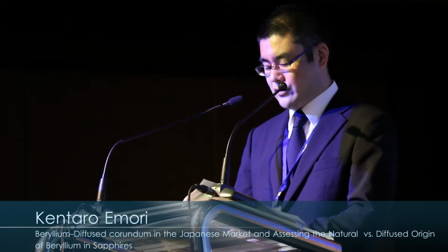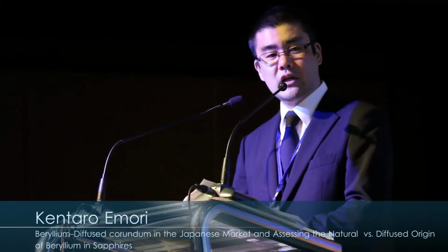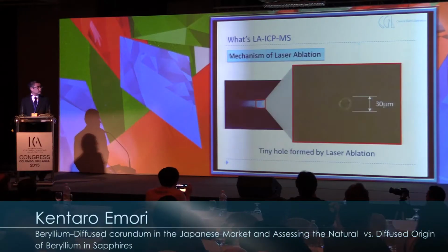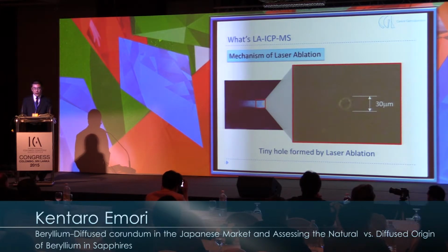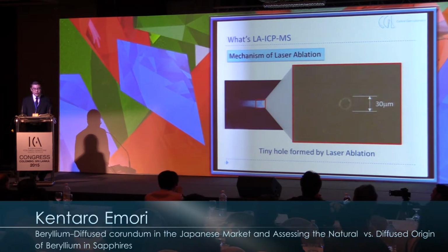Shorter wavelength lasers have higher energy, therefore a 213 nanometer laser is used for ablation in CGL. A hole is formed on the surface of the sample by laser ablation, but the marks are a few 10 micrometers, and we can hardly find them in a loupe with 10 times magnification. This test may be called a semi-destructive inspection because some damage is given to the sample. Therefore, we do this test after we get the consent of the customer.